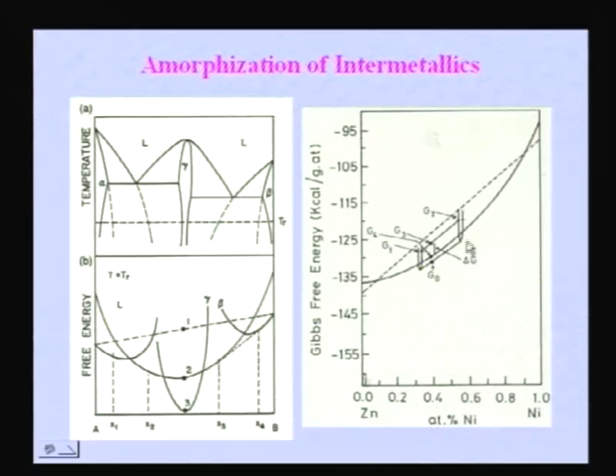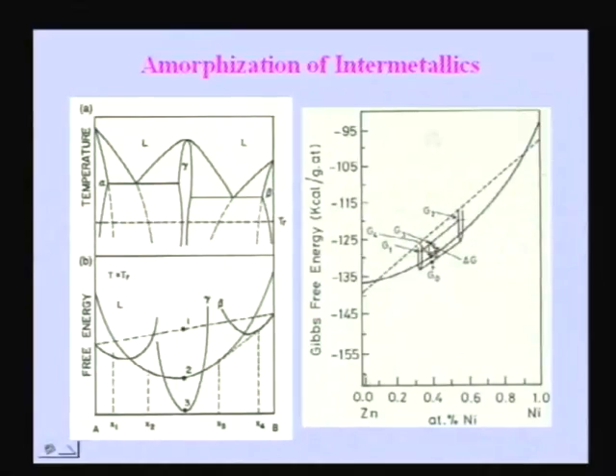And when you take a mixture of two intermetallics, let us say two intermetallics have been chosen here, one is this intermetallic, another is this, and the solid curve that you are seeing here is the free energy of the amorphous phase. The mixture of the two intermetallics has always the lowest free energy. Now if you again start ball milling, the free energy of the intermetallics goes up, and after some time of milling, the free energy of the mixture of intermetallics becomes something equivalent to G3, and from G3 to G4, where G4 is the free energy of the amorphous phase, there is a driving force, so now the transformation can occur. But directly from the mixture of intermetallics one cannot have amorphization, so one has to put in some amount of defects so that the free energy can go up and then transformation can happen.